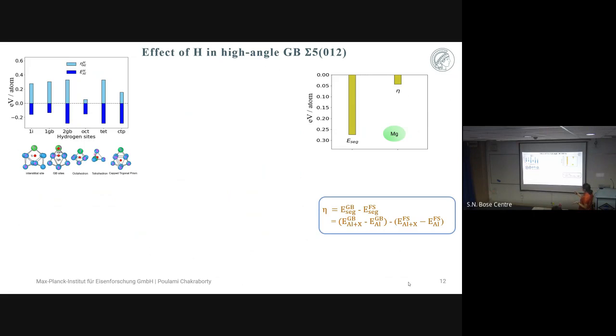Now coming to this diagram, you have already seen the lower plot. Each of the hydrogen sites is also shown here, what it looks like and where it is present. In each of these hydrogen sites, the top light blue color is the embrittlement factor. That is, when the hydrogen segregates to these sites, what is the tendency or probability that the hydrogen will prefer a free surface. Very interestingly, the sites which have the highest segregation energy, the sites where the hydrogen is happiest to sit, that is 2GB and tetrahedral sites, also have the highest embrittlement tendency. That is a very important point.